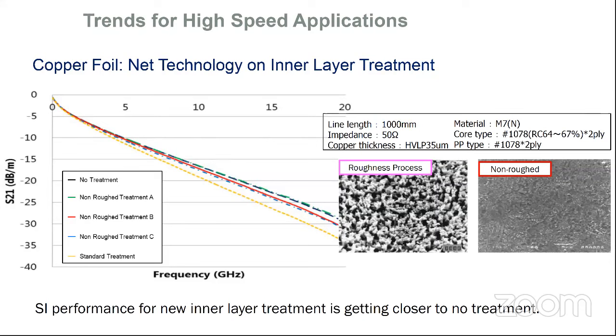The upper portions of the chart, we have no treatment, and these are actual chemical suppliers A, B, and C, but we just didn't list them. But as you can see, the non-roughened treatments, both A, B, and C, as well as the no treatment, are very close, in a close band, if you will, with regard to loss characteristics, as you compare it to the old standard treatment, which is the brown oxide.